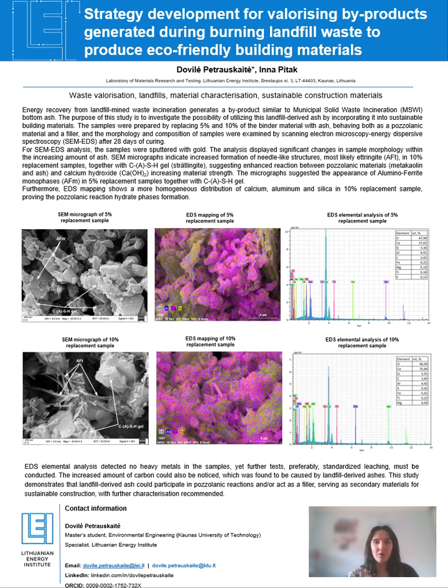So overall, these results indicate that the landfill-derived ash could participate in pozzolanic reactions and act as a filler, and it supports its potential use as a secondary material for more sustainable construction. However, further characterization is needed, including X-ray diffraction, FTIR, thermogravimetric analysis, and also mechanical testing to quantify the phase composition and also strength development.